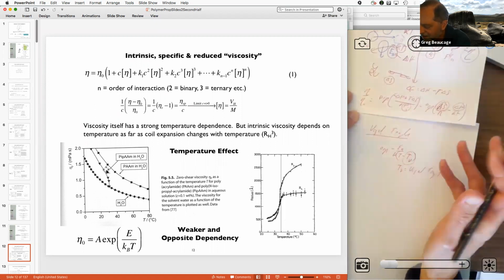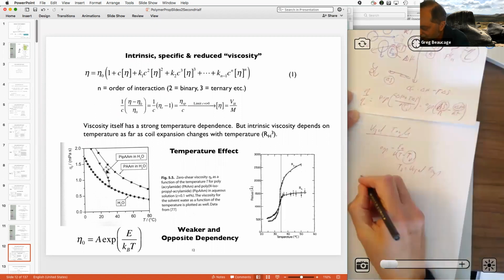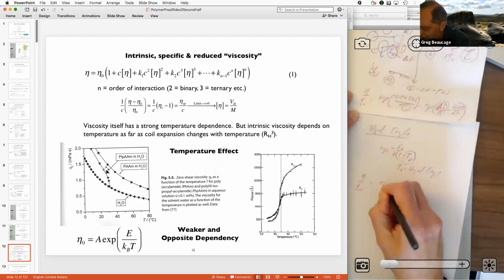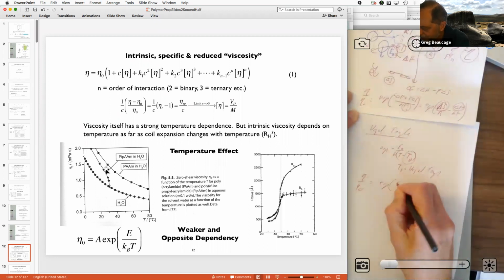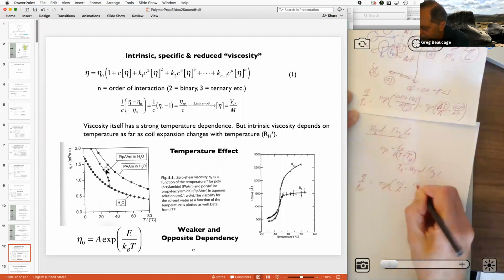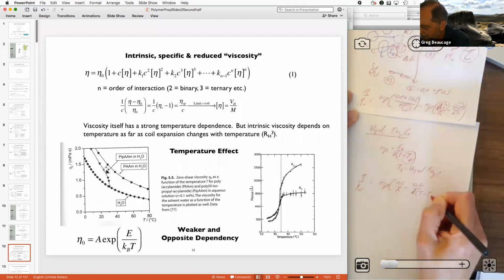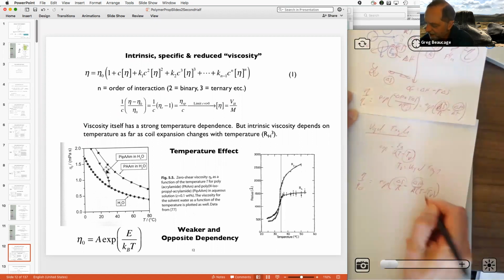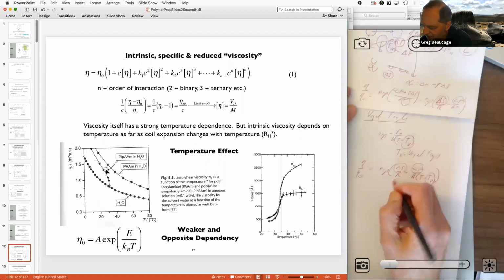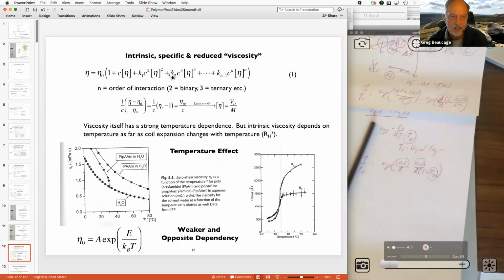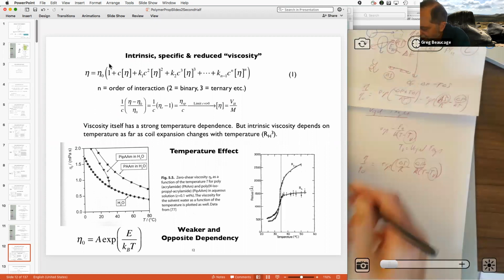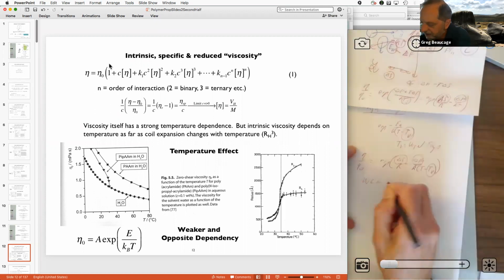Then you can have three parameters you can dump into this thing if you want to fully describe it: T minus T Vogel, this zero temperature. So there's 1, 2, 3 numbers you need. And you can rearrange that to be the Williams-Landel-Ferry WLF equation for viscosity.